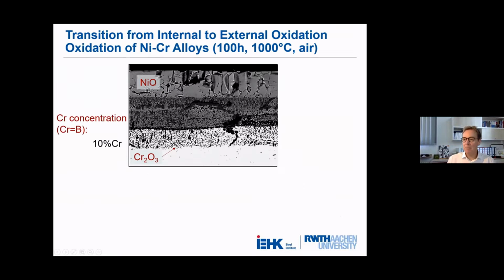Here we have an example. That is a nickel-10 chromium alloy. Here we see the formation of a nickel oxide wall, a fast-growing oxide, while at the same time we have the internal oxidation of chromia. Of course, due to the consumption of nickel during the process, part of the internal oxidation will soon be inside the nickel oxide.